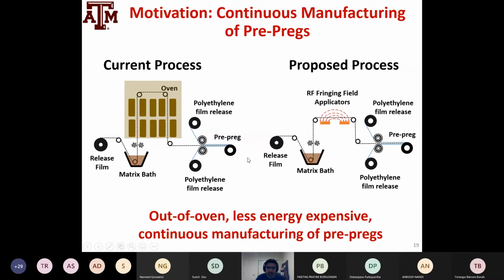You lay them up, and you make a composite. So we propose that instead of heating these carbon fiber composites in really large ovens, which are very expensive to operate, we'll heat them using RF field applicators. These are much smaller applicators. So it's a very easy, much less energy-expensive out-of-oven method for making prepregs for continuous manufacturing.